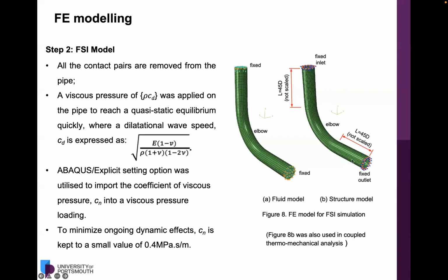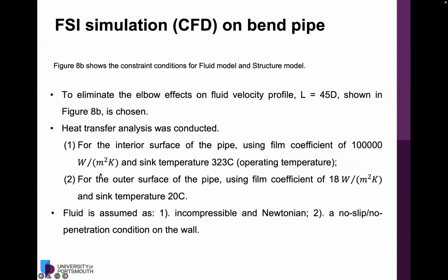For the thermomechanical analysis, we can refer to this figure 8b on the constraint that was introduced. So we are looking at the distance at length equals to 45 times diameter. And this is to eliminate the elbow effects on fluid velocity profile. We also introduced a film coefficient and sink temperature at the internal and external surface of the pipe during the heat transfer analysis. We make assumption that the fluid is incompressible and Newtonian, as well as has no slip or no penetration conditions on the wall.